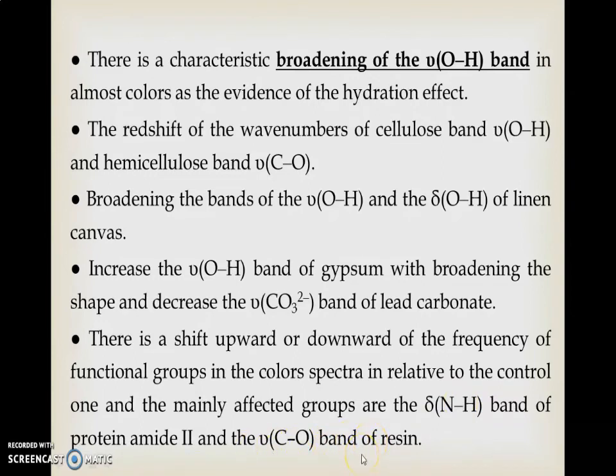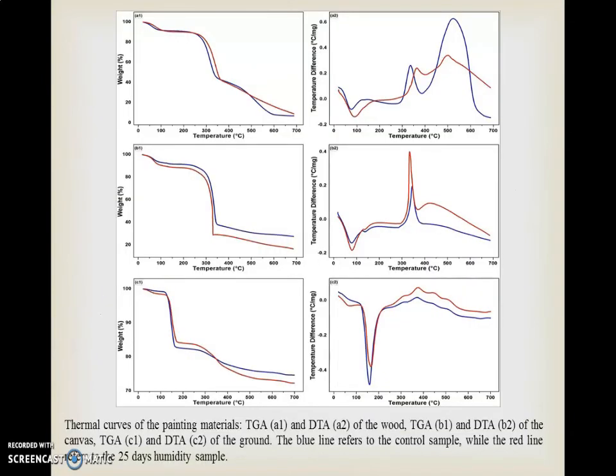Upon the fluctuation of the environmental conditions, the hydrogen bond can be broken to induce chemical and physical changes and the deterioration of the painting. Okay, the thermal analysis showed there was a thermal stability of the aged material with the composition at higher temperatures.